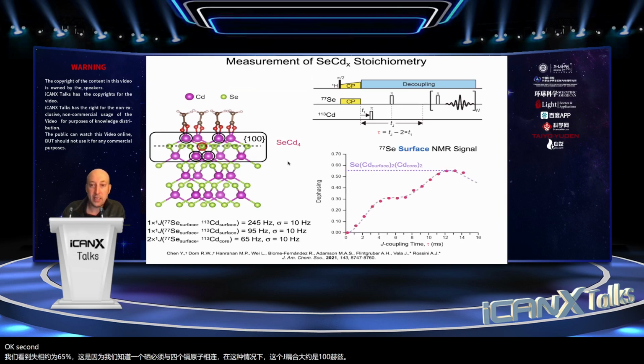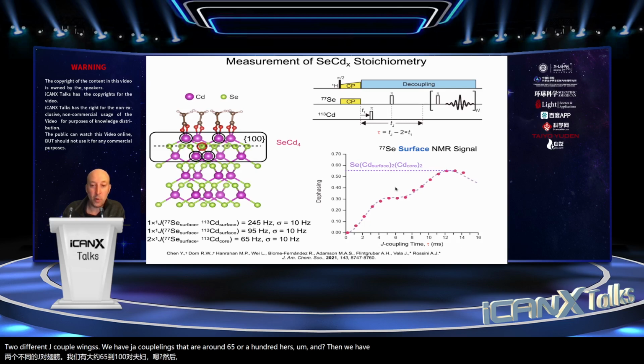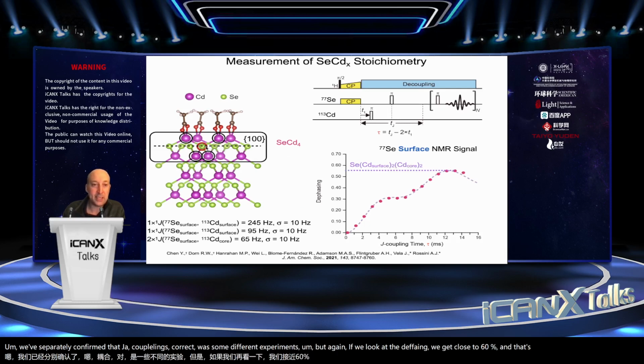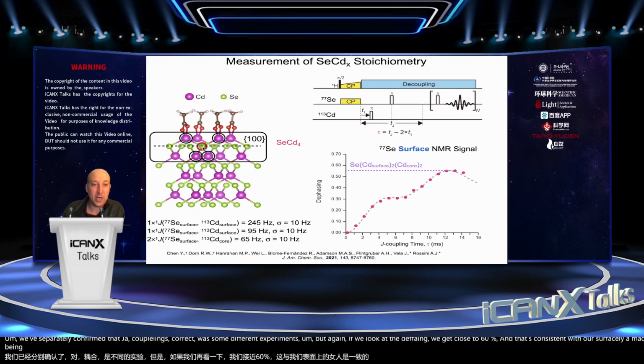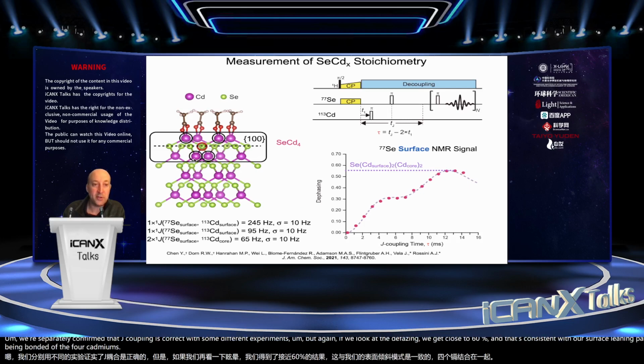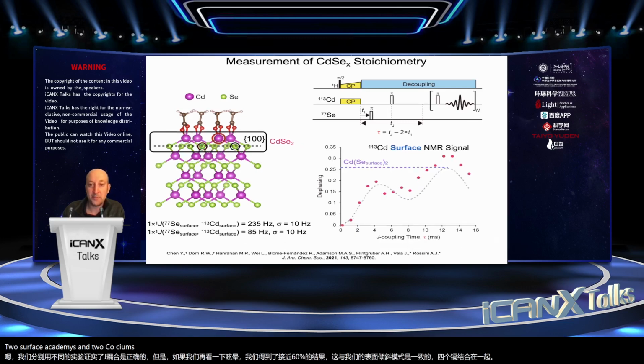Okay, second experiment then: we now look at the surface selenium atoms while we pulse on cadmium. What's interesting is we get 2 different J couplings. We have J couplings that are around 65 or 100 hertz, and then we have 1 J coupling that's about 250 hertz. We've separately confirmed that J coupling is correct with some different experiments. But again, if we look at the dephasing, we get close to 60%. And that's consistent with our surface selenium atoms being bonded to 4 cadmiums, 2 surface cadmiums and 2 core cadmiums.